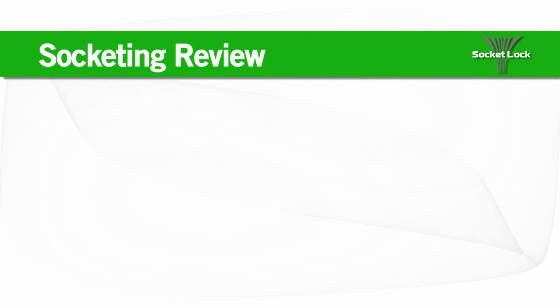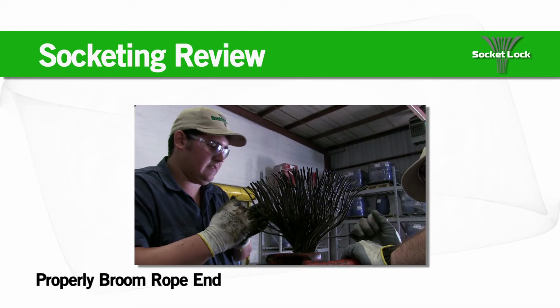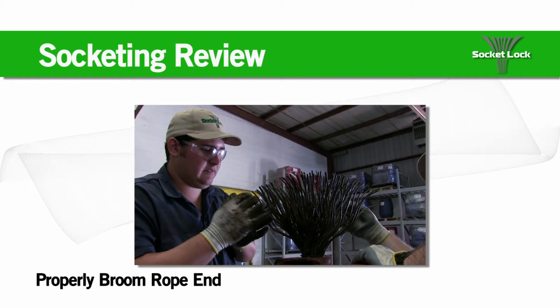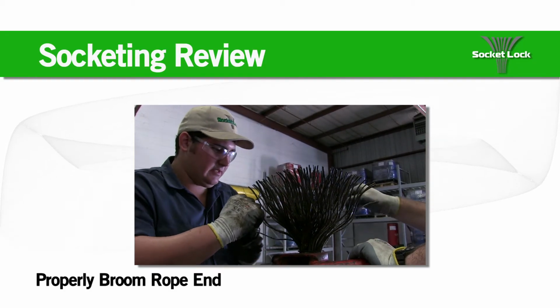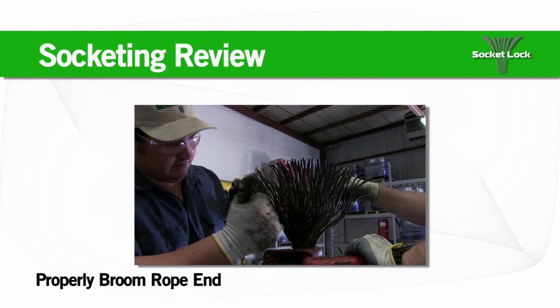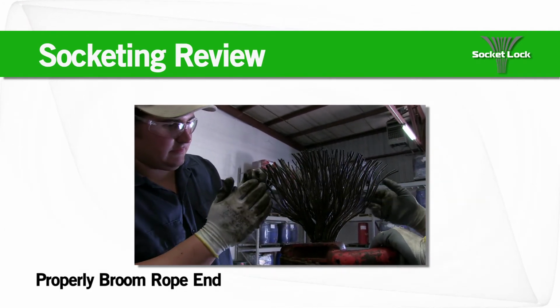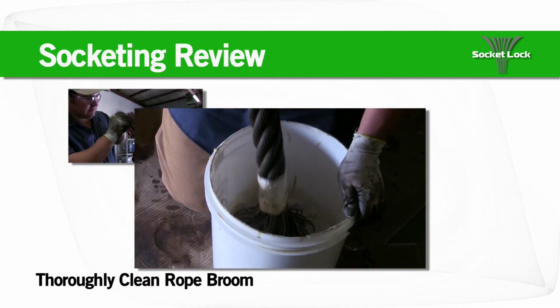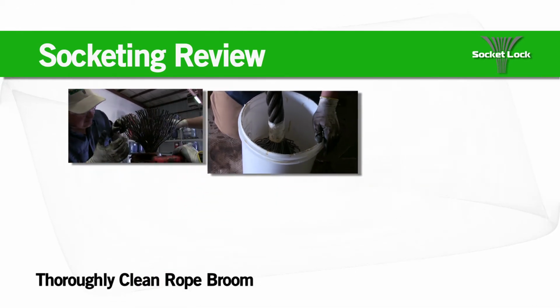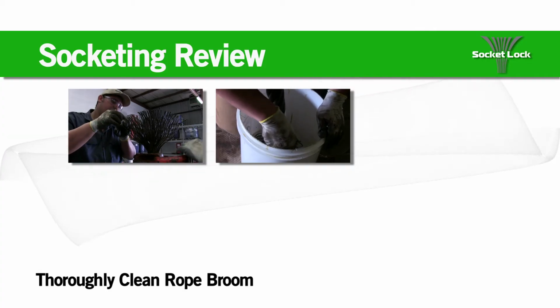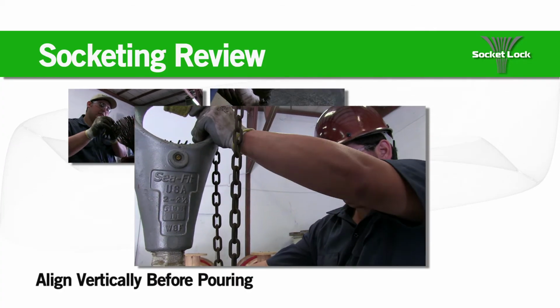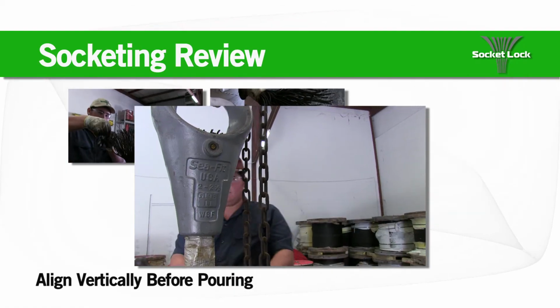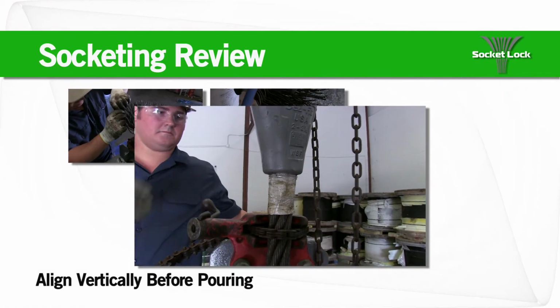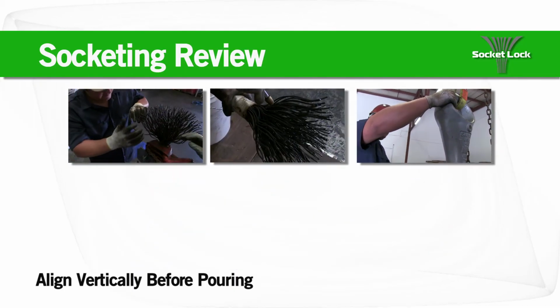A quick review of the key points to properly prepare the rope end termination with Socket Lock are: Make sure the end of the rope is properly broomed all the way down to the seizing. Doing so will ensure the resin reaches the bottom of the cone and fills around each individual wire. Be sure to thoroughly clean all lubricant and dirt from the broomed wires. Be especially sure to have the wire rope and socket vertically aligned with each other. Not doing so will cause unbalanced loading on the wires that may result in failure.